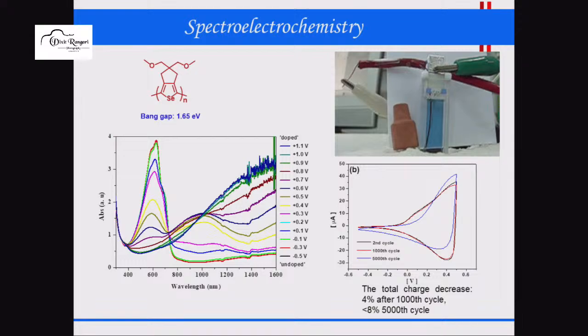Now you can see this is our spectroelectrochemistry study. In this one, what we did, we have taken this polymer which is coated on this ITO electrode and put connection with the electrochemistry instrument, and we have done this in a cuvette, and that cuvette we kept in the spectrophotometer. And then by changing the potential, we have plotted this particular graph, which is the absorption graph, but in the right hand side we have shown the various potentials. So you can see at some point your polymer gets oxidized and it forms the cationic charge.